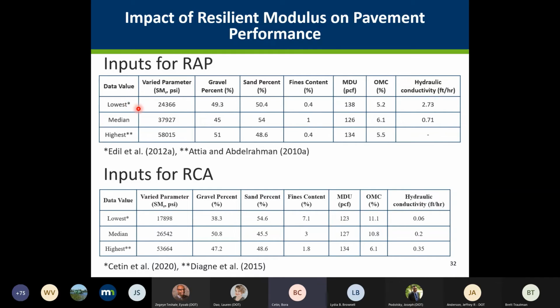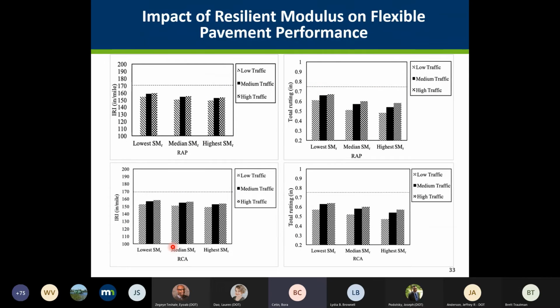And then with the lowest resilient modulus value, for instance, the lowest resilient modulus value was 24,000 PSI. So we found that report or paper that reported this lowest resilient modulus value, the SMR value for that particular material. So we picked the gravel percent from that paper or report that reported this lowest resilient modulus value, and used that as an input. Same with the highest materials. We did the same thing throughout the entire sensitivity analysis when we determined the materials with lowest and highest resilient modulus values. And then we varied the traffic conditions as we described in the previous tables, and we compared the IRI values.